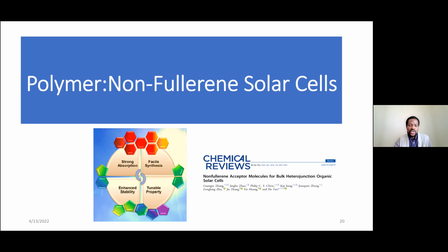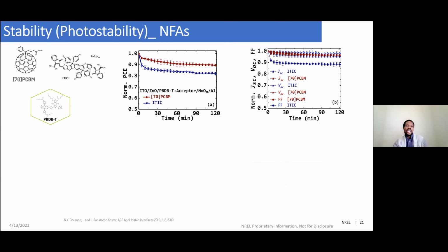So what we try to do is to look at the workhorse material, which is ITIC, and compare it to what we already understand with [70]PCBM. And clearly here you can see that in inverted structure, the ITIC device performs less, it was less stable than the [70]PCBM. So we tried to understand this.